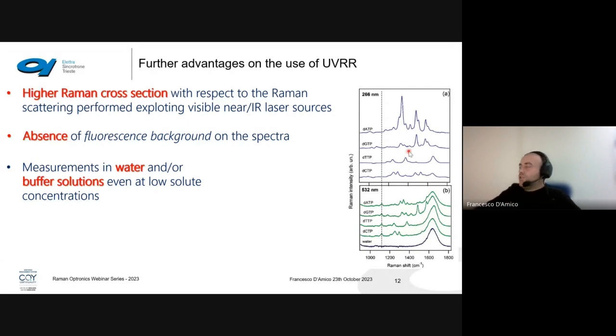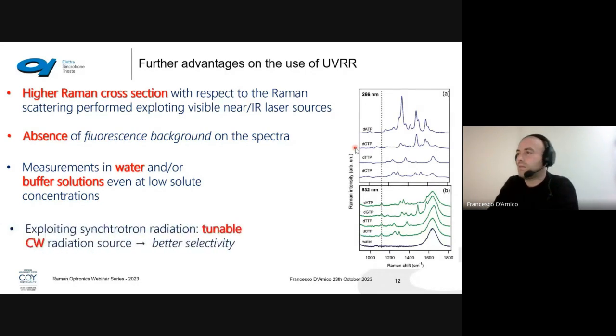The same concentration, with the spectrum done at 206 nanometers, so in the ultraviolet. In this case, we don't have this water peak, even if the concentration is the same, and we can appreciate a better, flatter background that allows us to make better considerations about the peak line shape. This is a strong advantage in case we would like to compare the line shape, as I will show you later, to make some considerations and data analysis.